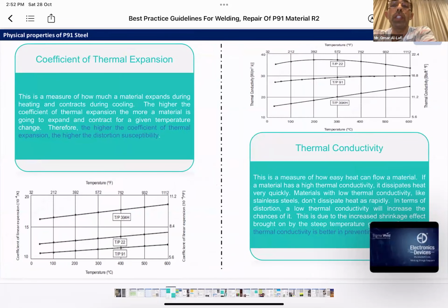The physical properties, I will speak about two properties here: the coefficient of thermal expansion. In the coefficient of thermal expansion, we know that the higher the coefficient of thermal expansion, the higher the distortion susceptibility. In part because when you have a high thermal expansion, the possibility of expanding during welding is more, and that will create more stresses and make it susceptible to distort during welding. So as we see in the table, in the graph, P91 material has a lower thermal expansion coefficient than P22